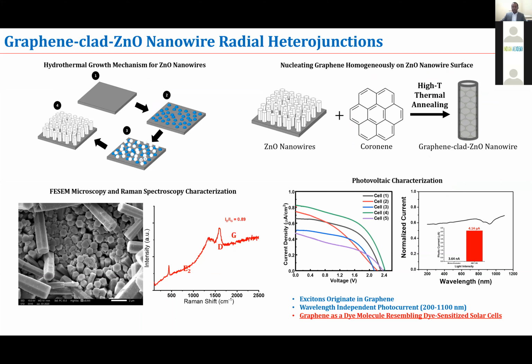As you can see here, the current is constant over a long wavelength range. If the current dropped at any point, then you could say that the light absorption or the charge transport is happening with the zinc oxide, but it is not. The current is constant over a long wavelength range, which corresponds to the fact that graphene is the material that is contributing to the photocurrent.